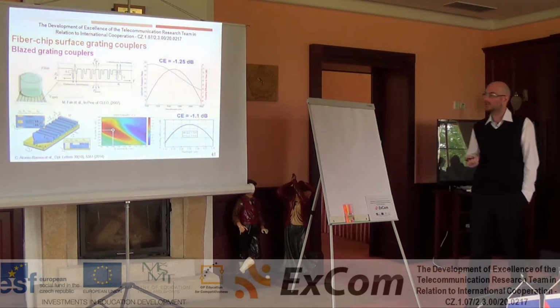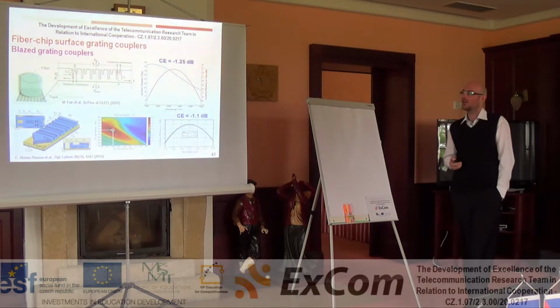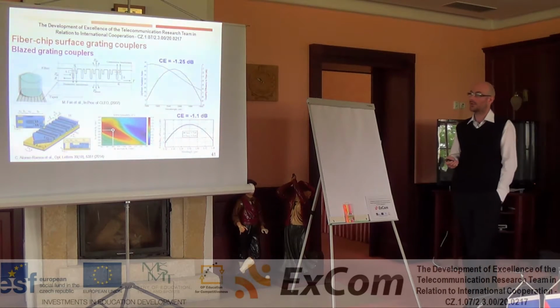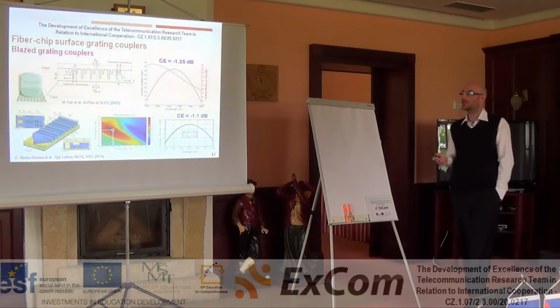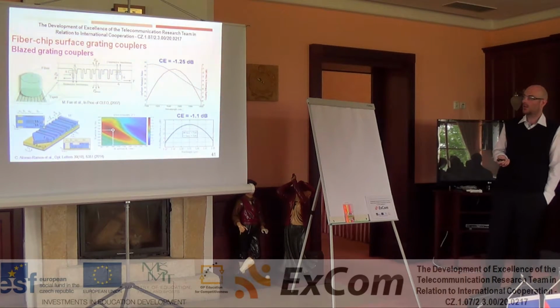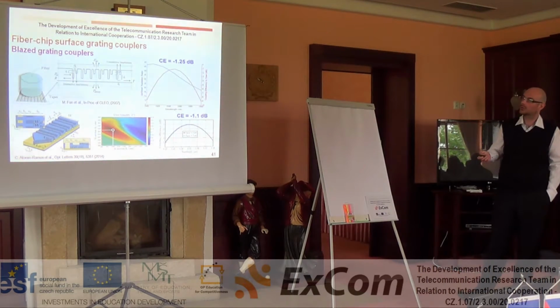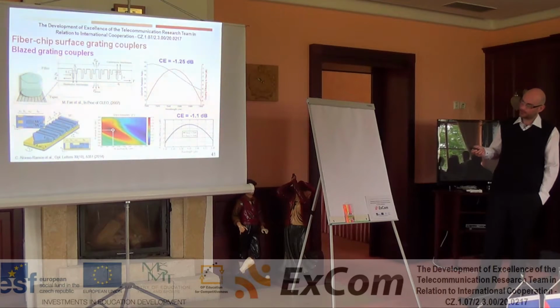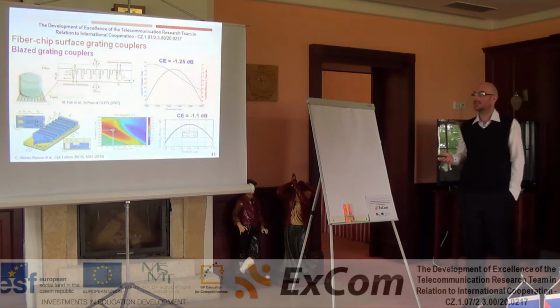The last approach to make very efficient grating couplers without backside processing or complicating the fabrication process is by utilizing the blazing effect in the grating. This was proposed for the first time by Fan, and they achieved a very high coupling efficiency of -1.25 dB. As you can see, you just need to interleave two etch depths in a proper way to achieve constructive interference for power that is coupled upwards, and destructive interference for power that is coupled downwards.